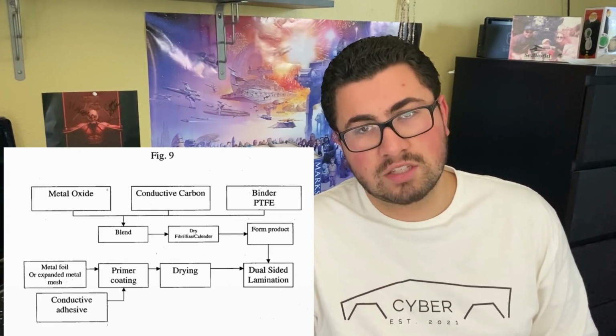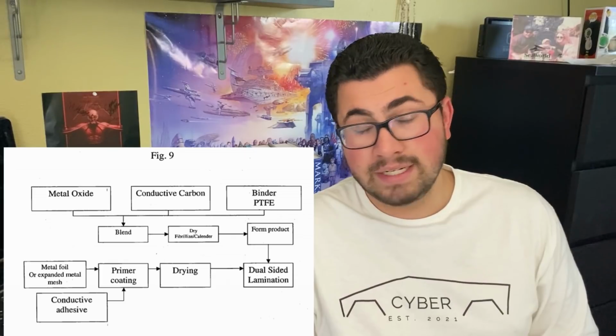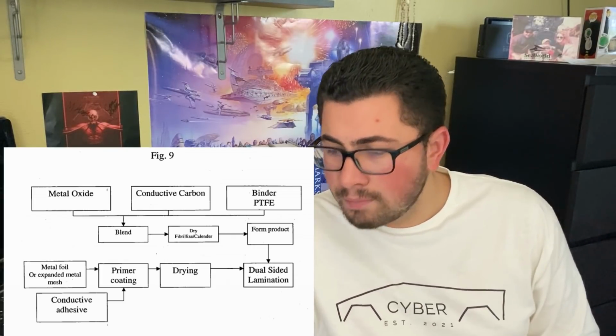You mix that with the conductive carbon and with the PTFE, which stands for polytetrafluoroethylene, and it's basically a synthetic polymer. One of the most notable types that they specifically list is Teflon. So they're basically putting Teflon in there and mixing it up. The binder that they're including is totally dry. And it's important to recognize that the patent also mentions a couple of other types of dry polymers as well, for example, polypropylene, polyethylene, copolymers, and blends of different polymers.